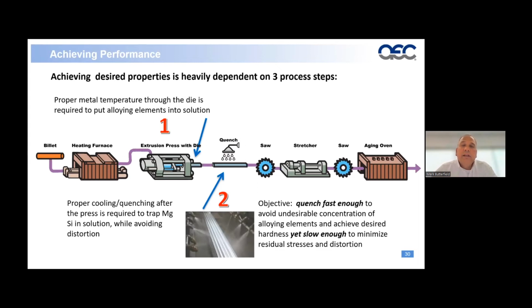Now, a lot can be done in this area, but this is one of the main reasons why the development of a specific alloy or chemistry is so critical, because we can adjust or modify the quenching process relative to those specific chemistries and help minimize the distortion while maintaining the product performance the product requires. And then finally, proper aging through the aging oven to fine tune those final properties.